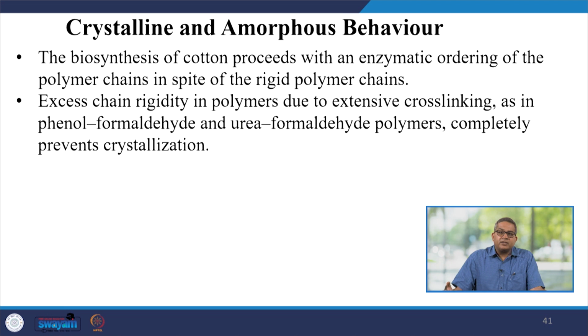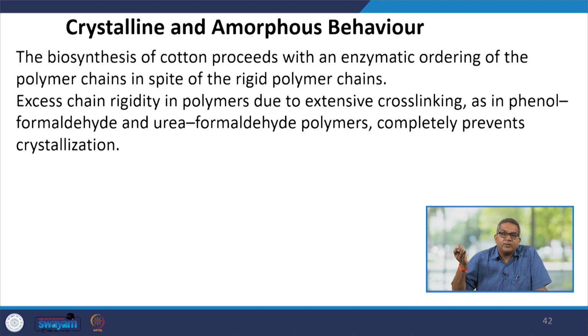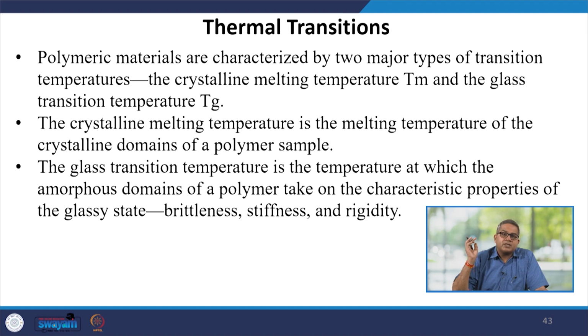Excess chain rigidity in the polymer is due to extensive cross-linking, because cross-linking always hinders the free movement of the chains. This is reflected in phenol formaldehyde and urea formaldehyde polymers, where it completely prevents crystallization. Sometimes excess chain rigidity causes several processability problems, which can be reduced by applying various additives during the course of processing.